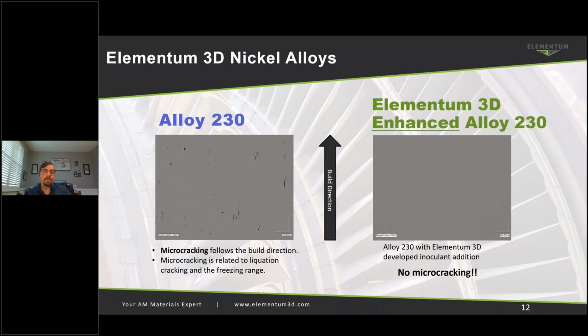Our most recent work has been in Haynes 230 alloy, where we're modifying that alloy with our inoculants, and we're seeing a lot of different benefits. So you can see some cracking here on the left. It might be difficult to see, but you can see these kind of cracks that are running through. That goes away, along with a lot of the porosity that we would typically see that can be caused by the same kind of columnar grain structure.